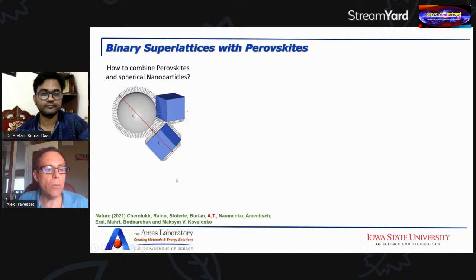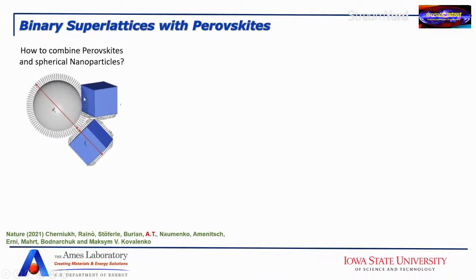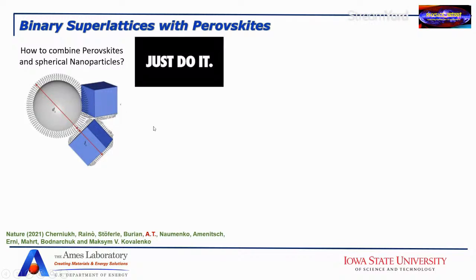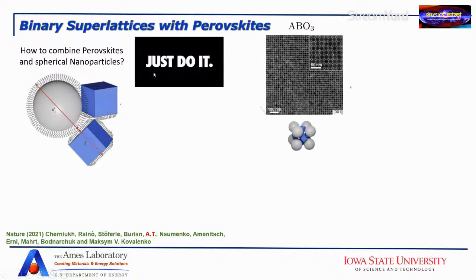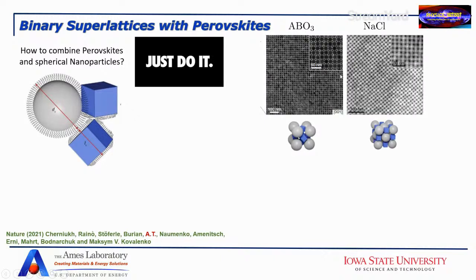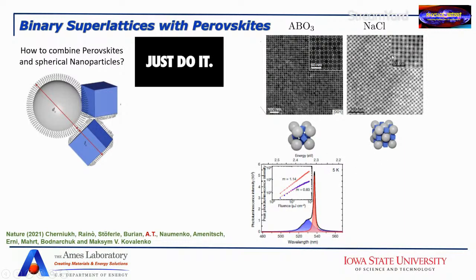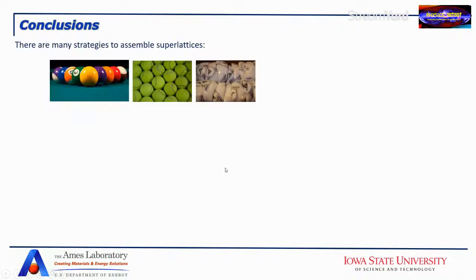So in our recent paper, the one that appeared in Nature today, what we did is we combined spherical nanoparticles with cubes. And how to do that? Well, you just do it and it happens. So we have here two structures, ABO3 and sodium chloride. You can see here that the cubes are ordered and oriented in different ways. Here you see this is actually a simple cubic lattice of spherical particles. And then you have cubes that are oriented in a different way. And here the sodium chloride. What is interesting is that this one has superfluorescence, but this one does not. So superfluorescence remains only for ABO3, but not for this one, showing that the structure has a fundamental role in determining the superfluorescence properties.